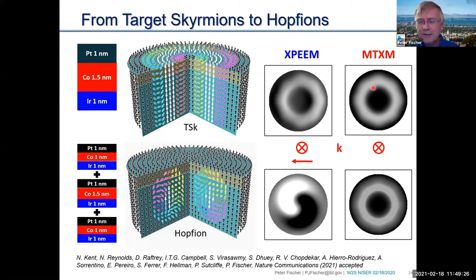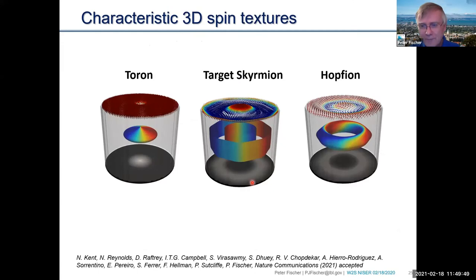But when you combine the results from a transmission geometry with the surface sensitive PEEM, you should be able to distinguish whether this system has generated a target skyrmion or a Hopfion. And this is exactly what we did, and the paper was just accepted last week. Now we did a little bit more simulations on this. These characteristic 3D spin textures for the Hopfions would also be distinguished from not only the target skyrmions, but also something that's called a toron.